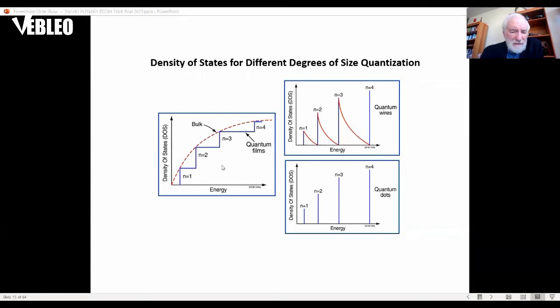So this just shows the density of states for different types of quantum regimes. You can have a thin film where you're only confining electrons and holes in one dimension. So that would be a film, and then you have a stepwise density of states. If you have a wire called a quantum wire, you would have a density of states function like this, where you do have some densities of states in between the discrete states. And then in the limit where you confine the material in all three directions, you would have what's called a quantum dot or a nanocrystal. And then this looks like a molecule almost. You have very strong discrete states with no states in between the quantized levels.